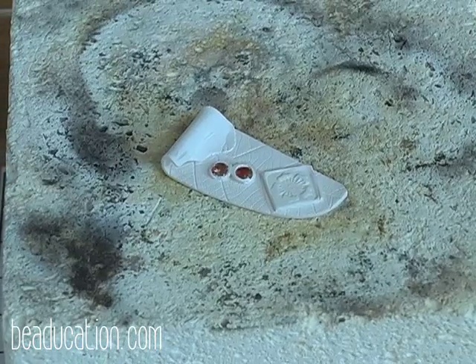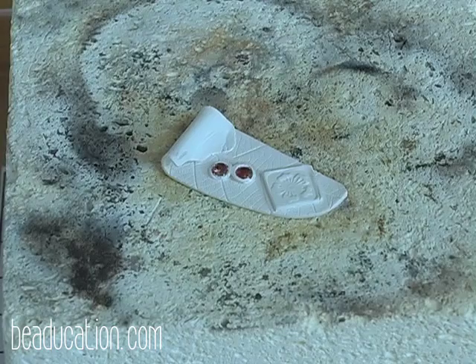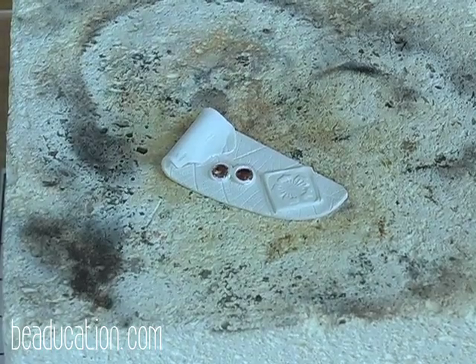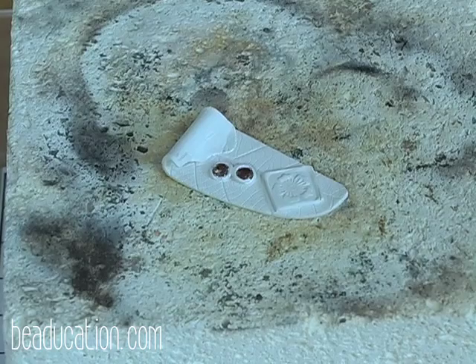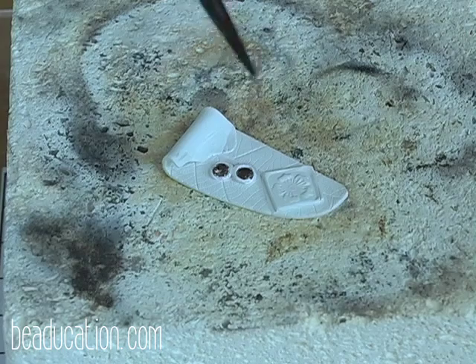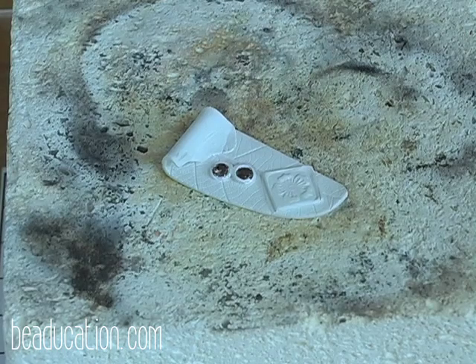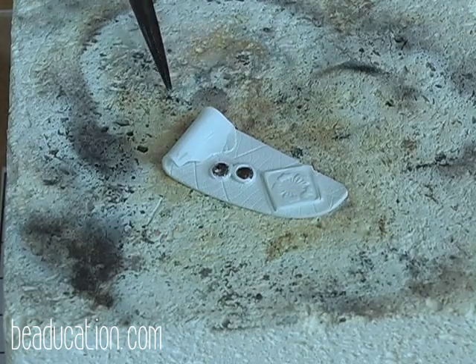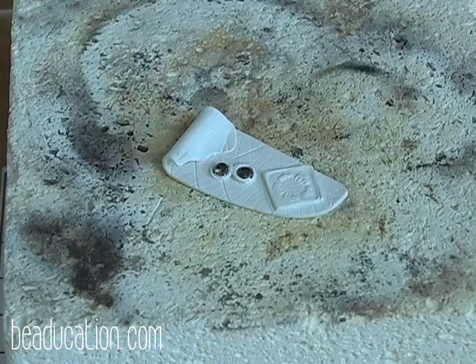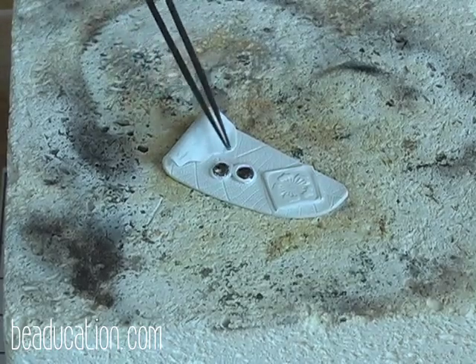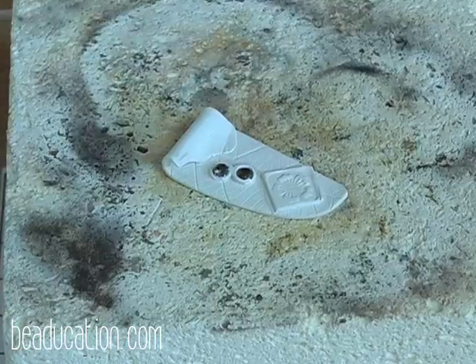Now you can see it's starting to cool pretty rapidly, but we were really on there for quite some time with the torch. So kids, this is pretty hot, so you do not want to touch your PMC. We want to make sure that we let this cool naturally rather than quenching it in a bowl of water. If we quenched it in a bowl of water, these stones would crack due to thermal shock.